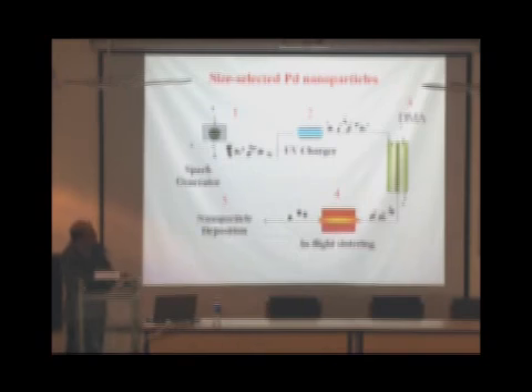But you can say that they still do not have the same shape. Then the particles are taken to a sintering furnace. The gas takes them, there is no substrate effect, and the particles are still floating in the gas. They form spherical droplets, and when they come out they are monocrystalline and spherical in shape, and they have the same size because of the differential mobility analysis. What is important here is that these are positively charged particles because the central electrode was given a negative voltage. If you give the central electrode a positive voltage, you can select negatively charged particles. This is important, as I will show you later.